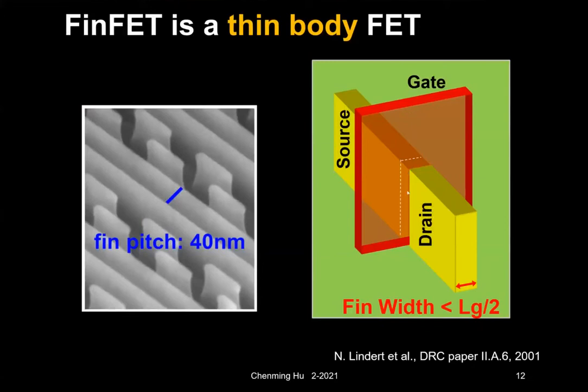But of course, oxide thickness is still beneficial. That's why we are using 0.7 nanometer EOT now. And in fact, we also pointed out a quantitative correlation. That is, if you can make a certain thin thickness, then the gate length can be as small as twice the thin thickness. You know, this number 2, of course, you can argue whether it should be 3 or what. It depends on your spec for leakage current. But basically, if you can scale the thin thickness, then you can reduce the gate channel length.